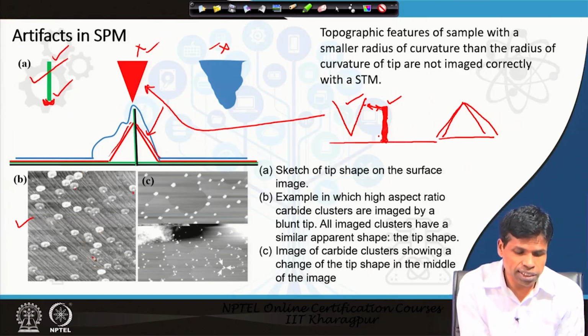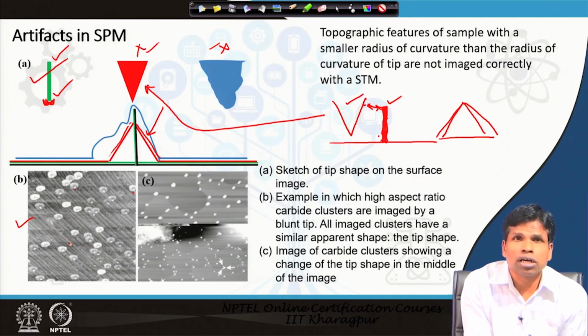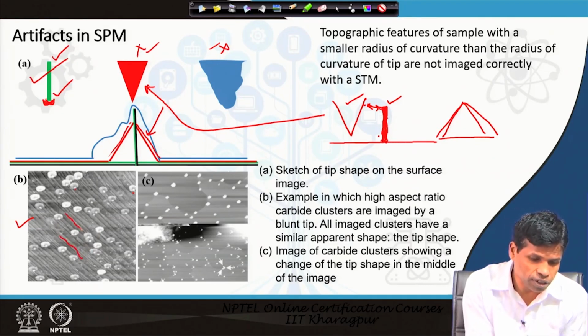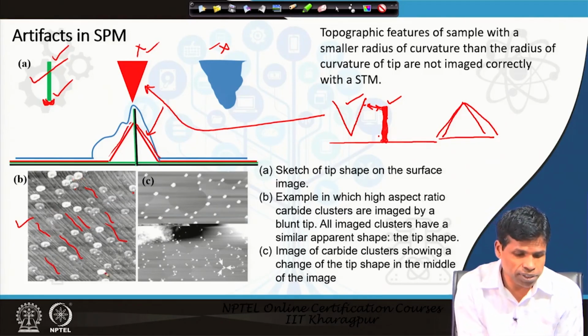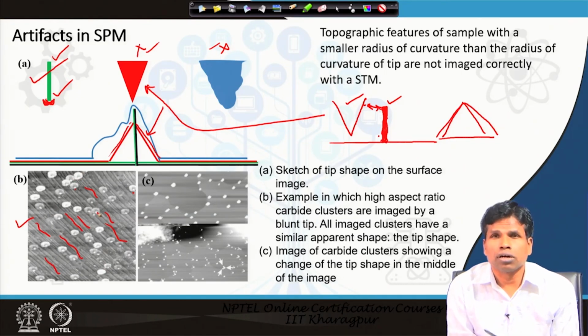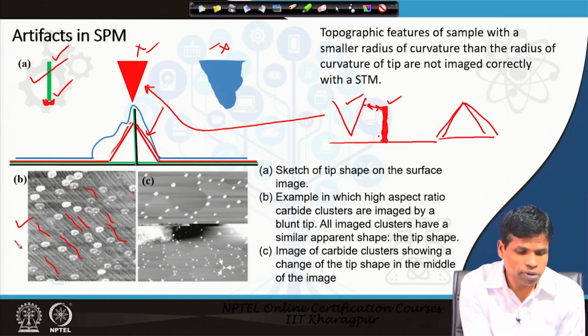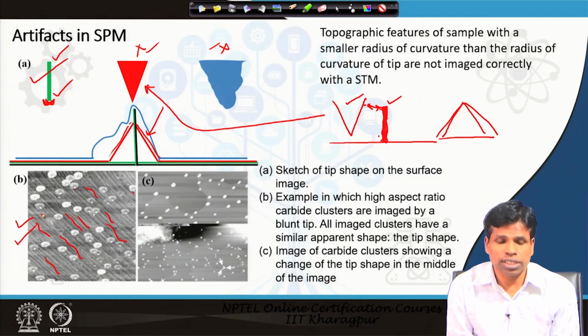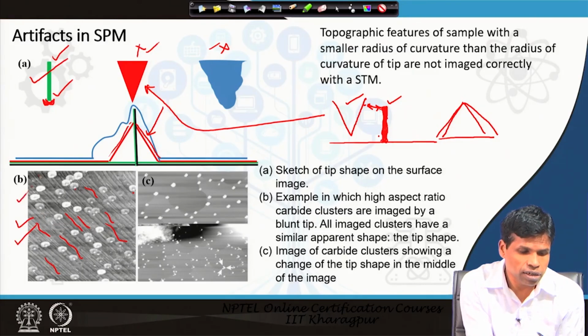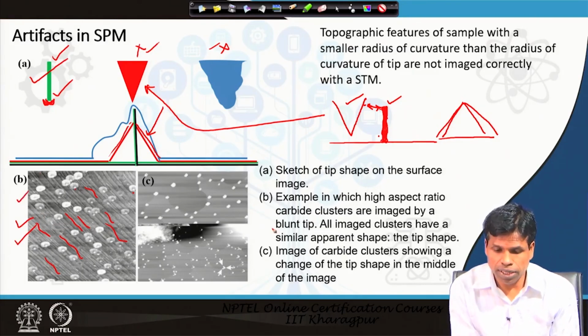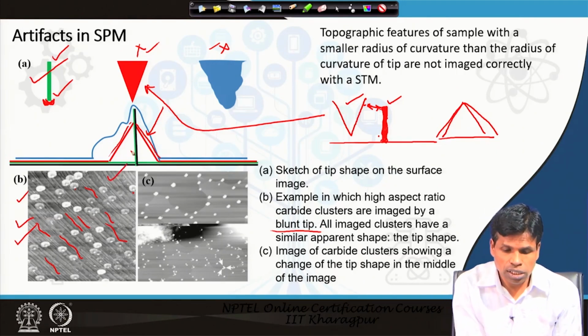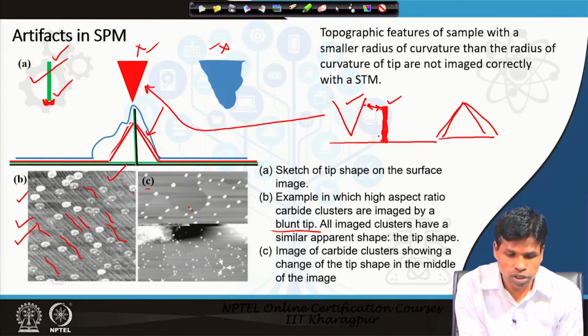What we could see is that in addition to the carbide clusters, in the background there are one-dimensional directional features, and all these particles appear of similar shape with the middle portion brighter than the surrounding portion. This type of image indicates there is an artifact, something wrong with the tip. This image was collected with a blunt or not sharp tip, showing the image of the tip only, not the actual sample.